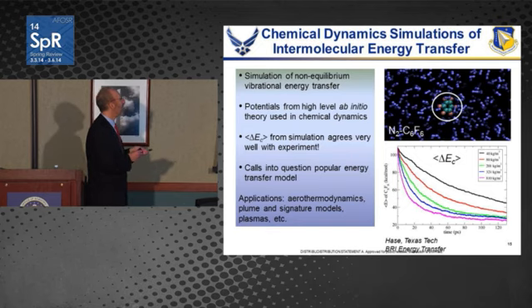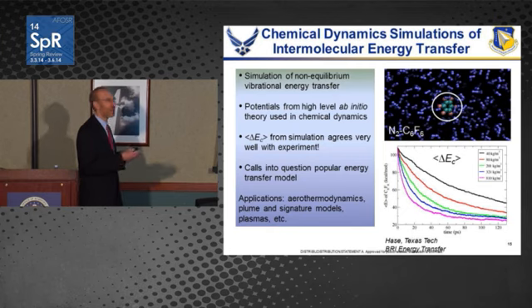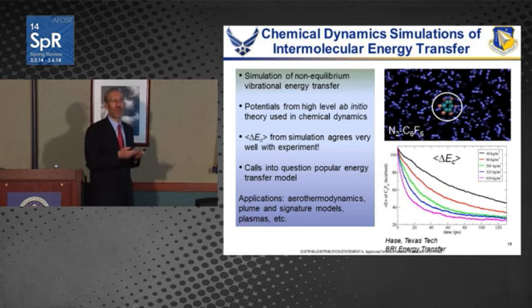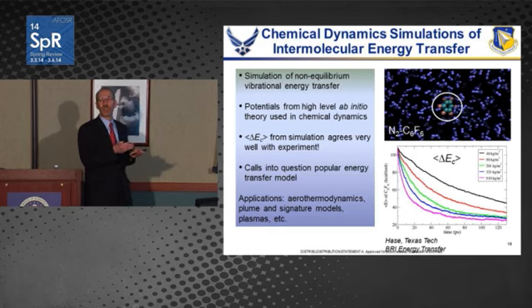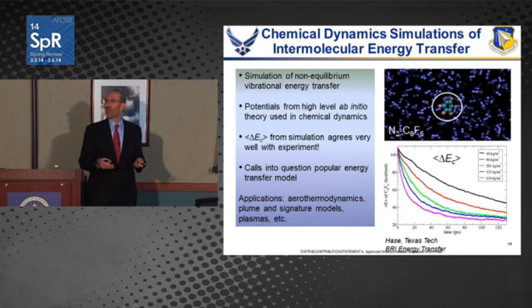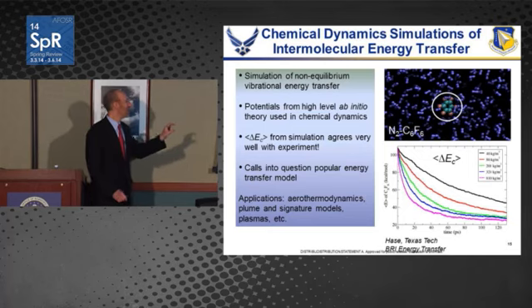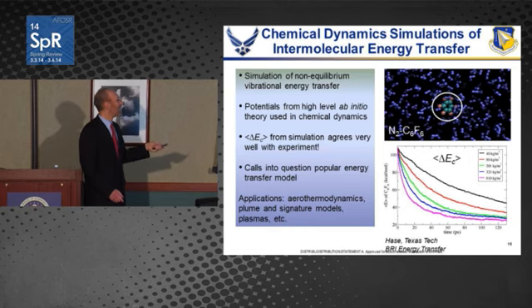And the nice thing is in these calculations, Bill has done high-level ab initio calculations to get the interaction potentials to do the chemical dynamics. And from this, he's found that the energy transferred per collision that he can simulate agrees quite well with experiment, but it conflicts with or calls into question a commonly used model in this energy transfer field. That's a model called delta E down that says there's a particular energy per collision that can be used throughout the energy regime. And Bill finds much larger energy transfer per collision at higher energies and smaller amounts of energy transferred at low energies. But these types of simulations and this type of interaction is the type of thing that the chemistry community is bringing to the aerothermodynamics community, and hopefully it can be incorporated into their simulations.